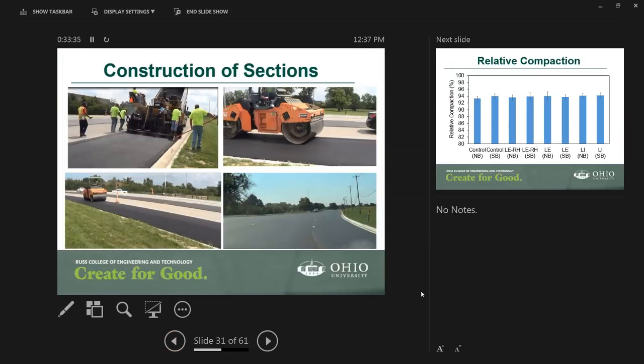So the construction of the test section: all GTR mixes were constructed in the same exact way as the polymer modified, with the same equipment and everything the same. Even the rolling pattern was the same. So we monitored compaction temperature and density. Density in this project was obtained using the PQI 380, a non-nuclear density gauge.